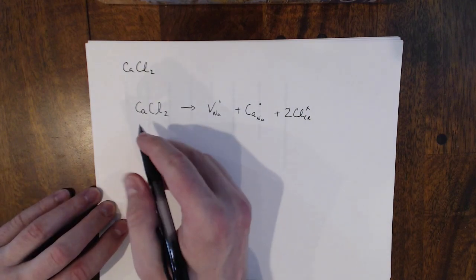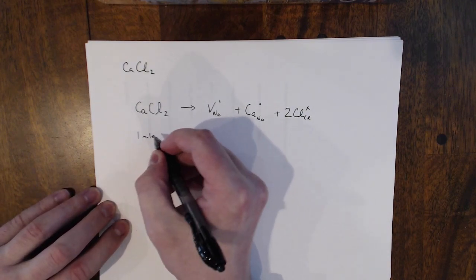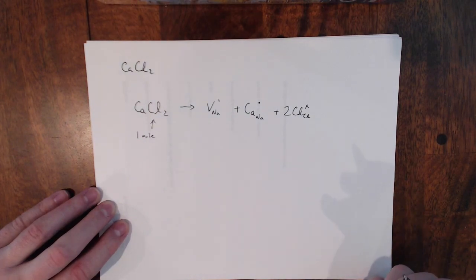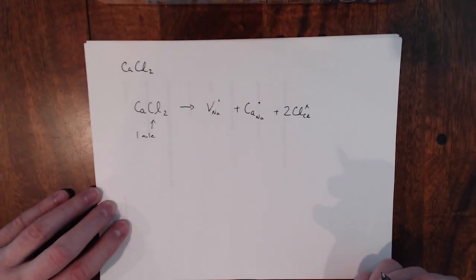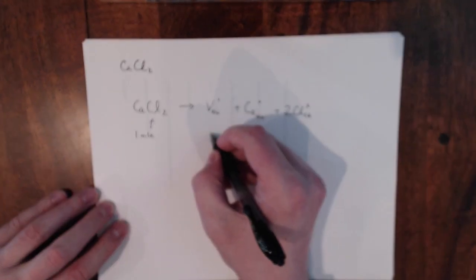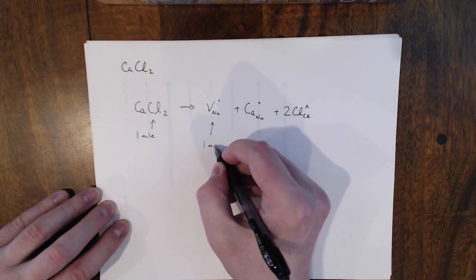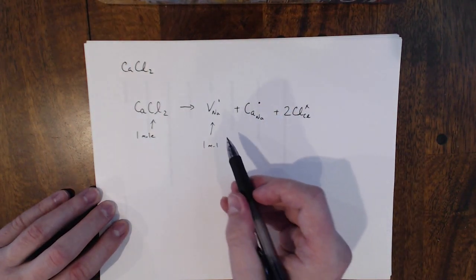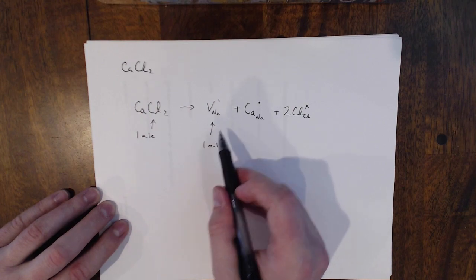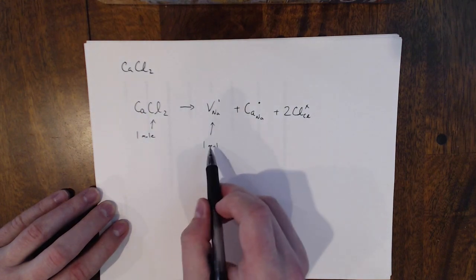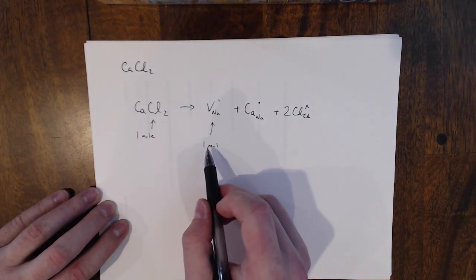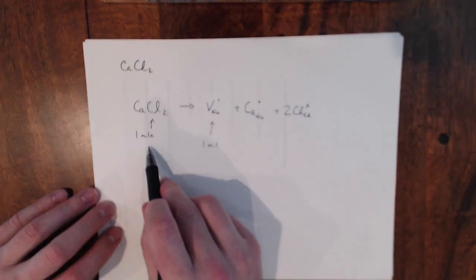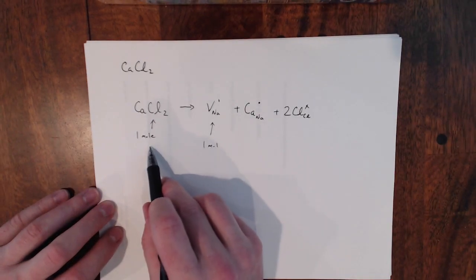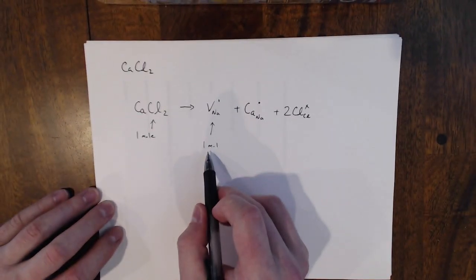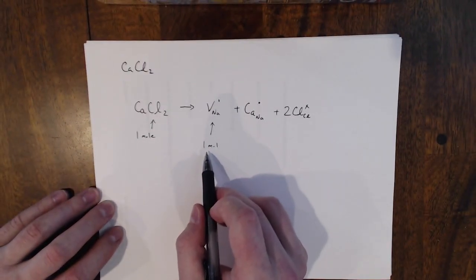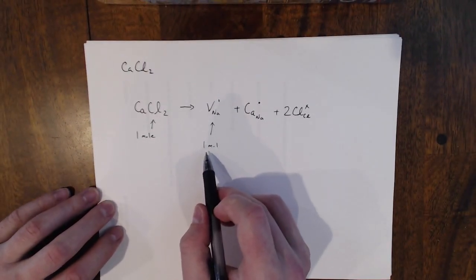All right, so the important thing that we're going to look at here is that if I add in 1 mole of this calcium chloride, I'm going to get 1 mole of these sodium vacancies. It's a one-to-one connection between those two things, right? So for every 1 mole of calcium chloride that I add, I'm going to get 1 mole of sodium vacancies. That's what we can kind of get from this.